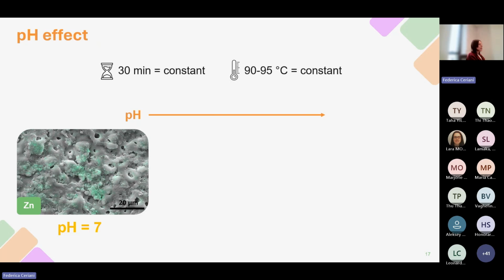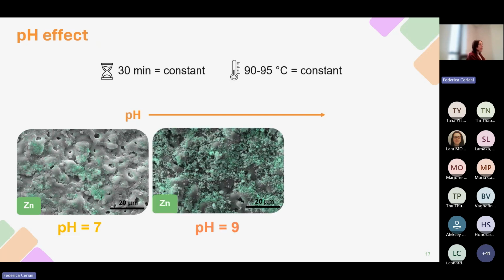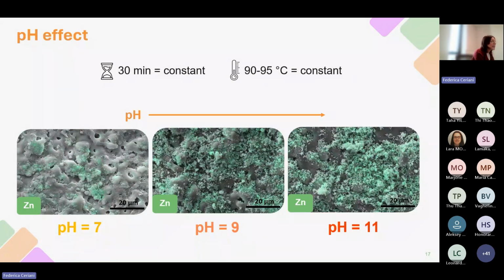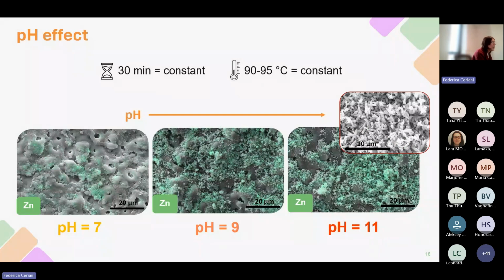In the second case, an initial pH of the solution equal to 9 is tested, and in this case, again, we observe the presence of small lamellas spread on the surface. And in this case, the sealing effect is enhanced with respect to the case of the more acidic solution. Finally, an initial pH equal to 11 is tested, and in this case, more numerous and larger lamellas having petal-like shapes are produced. And even in this case, a great sealing effect is obtained.